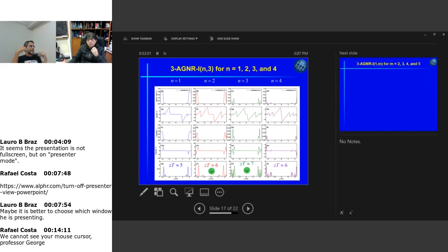And then all the excitement was generated when ZT went from 1 to 2.5. And we need to be at ZT equal to 4, as I told you, to have something interesting. Well, it's clear that this here is just a calculation. It's a relatively accurate calculation because tight binding describes these materials well. I forgot to mention that we modeled the Hamiltonian of the system here using the tight binding method. But tight binding is very accurate for these materials. So any increase that you get in ZT should be considered important. So 10% is already something to be happy about.